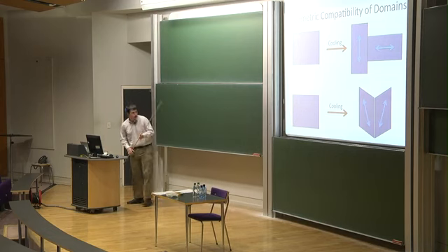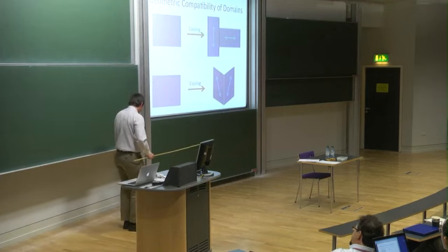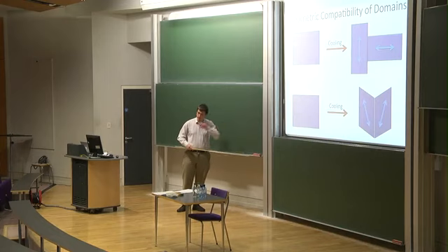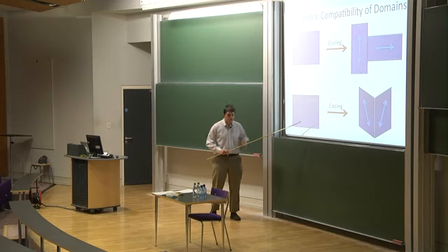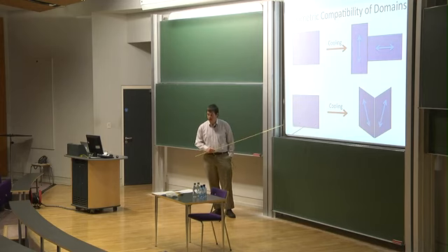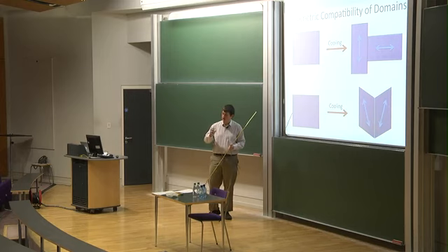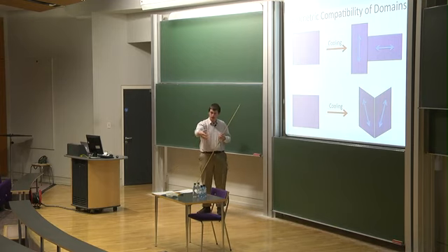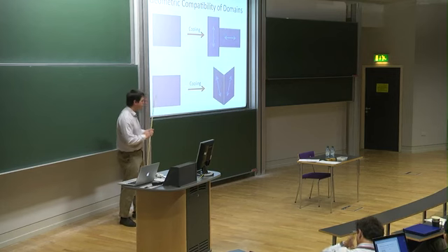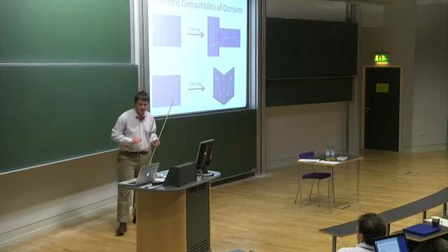So cooling under the condition of being a solid places a very harsh constraint on what kind of domains can form. Now, the really important thing here is, if I'm forgetting that alpha term, that anchoring term, and I just have the big term, then one definite possibility is that by happenstance, every single domain chooses to align in the same direction. That's definitely kinematically compatible. It will result in the solid macroscopically extending, and it's definitely a low energy state because each part of the elastomer has extended by r to the 1/3. So if I didn't have that anchoring term, then the state where it fully aligns, and therefore stretches with respect to the isotropic parent state globally, is definitely a low energy state.